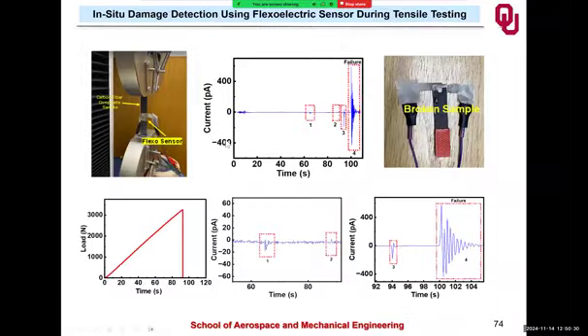Another application we also explored is in situ damage detection while doing mechanical testing. For this purpose, we attached our sensor to the composite sample and stressed it. A very interesting result is that when the catastrophic failure happens, the sensor is able to detect that signal, and that tiny signal is also captured by our sensor. So we can say that it is also capable of in situ damage detection.